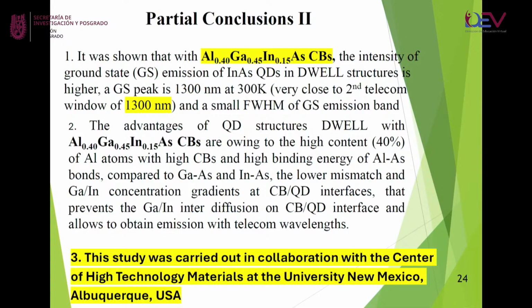This is a short conclusion concerning the second part. We show that the confinement barrier with this composition, with 40% aluminium, permits receiving intense ground state luminescence, with a wavelength of 1300 that is necessary for the second telecommunication window, and a small full width of the emission band.